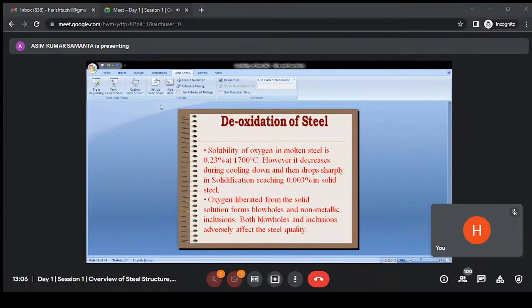Then what will happen to the oxygen entrapped within the steel? Some porosity will be created, and a non-uniform grain structure will be created in the steel. So, during refining of the steel, we need to allow the oxygen to come out. Now, oxygen will not come out very easily. We use elements like manganese, silicon and aluminium, so that manganese oxide, silicon oxide or aluminium oxide is formed, and oxygen is taken out in oxide form. This is called deoxidation of the steel. However, this process is quite costly.